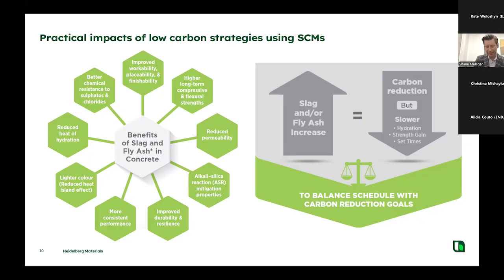But generally speaking, as you start to substitute higher levels of fly ash or slag, you start to see impacts on the performance of your concrete mix, some of which include increasing the curing time, so slowing down the schedule that strength gain is happening within that concrete matrix. So that might not be an option past 20% in fly ash, for example. As you start to move to 25, 30%, 35% substitution, you might be incurring schedule impacts to your concrete that are just not acceptable with your construction goals.